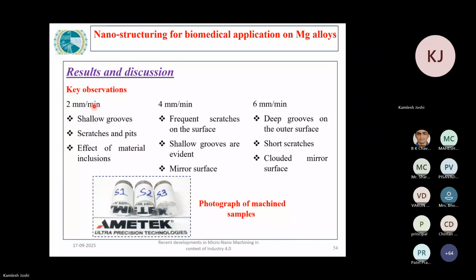When the feed was kept at 2 mm per minute, shallow grooves were observed on the surface along with the scratches and pits, and the effect of material inclusions was also observed. After increasing the feed rate to 4 mm per minute, frequent scratches on the surface were seen, shallow grooves were evident, and a mirror surface was achieved. With further increase in the feed rate, deep grooves on the surface were observed, scratches were observed, and the mirror surface was converted into a clouded type of surface.